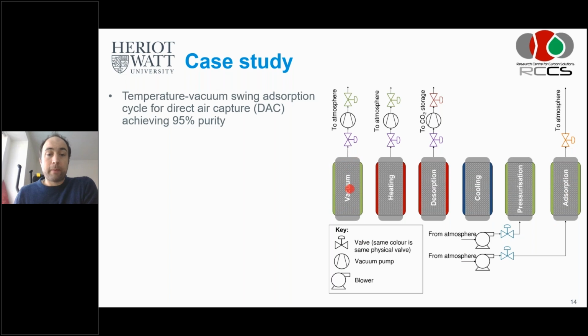So we first evacuate the bed to get rid of all the nitrogen and oxygen. Then we heat up the bed, still while having the bed open to the atmosphere, to get rid of even more nitrogen and oxygen and water as well. And then we heat further, and we do a desorption step where the CO2 comes out relatively pure, only contaminated with water. But water you can knock out easily in a water trap. And then it can go to storage, or it can go into a greenhouse, or you can use it for power to X or whatever you want to use it for.